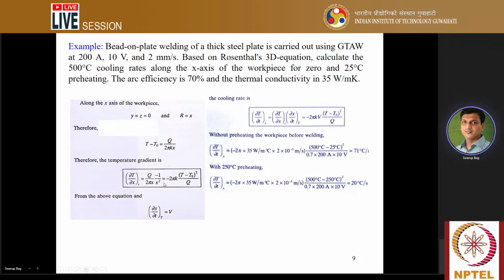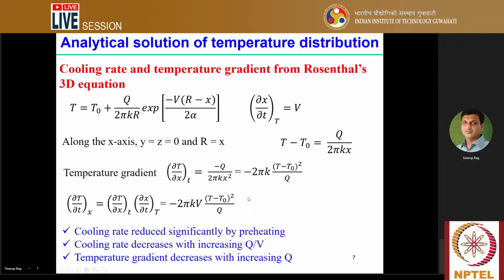Therefore, we can calculate the temperature gradient, del T by del x. That accounts for minus Q by 2 pi k x squared, which equals minus 2 pi k (T minus T0) squared by Q. This we have already calculated. Here you can see the temperature gradient is minus 2 pi k (T minus T0) squared by Q. So the same thing is written here.